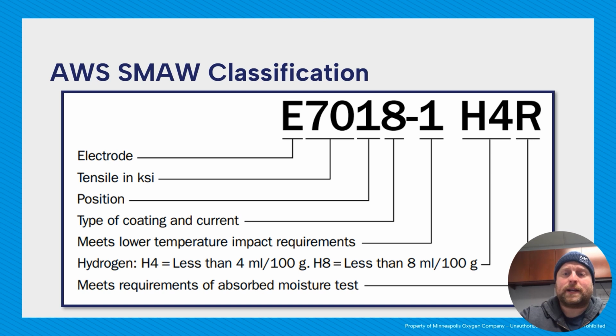Because of that, when we heat up metal, those unit cells that I was talking about previously move apart. That's what causes the metal to go from a solid to a plastic state and then a liquid. As they're moving apart, there's more room between them, and since hydrogen is such a tiny atom, it can just scoot right in there. Once it solidifies, if the hydrogen has not had a chance to be removed, it gets trapped, and you get what's called cold cracking or underbead cracking. Some types of welding, like in shipbuilding, get inspected about 2 weeks later, because that's how long it can take for that crack to develop from trapped hydrogen. So not having hydrogen is a really big deal. That's also why we have the absorbed moisture test, because moisture has hydrogen in it. It's not exactly the moisture that's the big issue, it's the hydrogen component of the moisture.